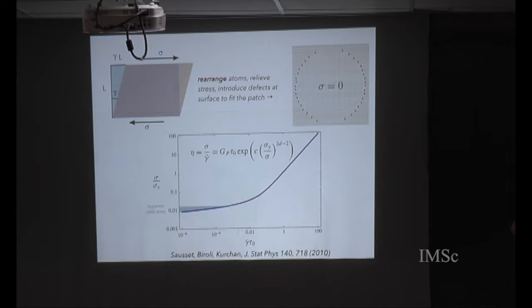But once you shift them back, you will have a boundary. This is a single crystal, but once you shift them back, you will have a boundary, and the energy will be completely localized at this boundary, where you have to put in dislocations. So now you can make a typical first passage time like calculation, and from the time and from the stress which you have relaxed, you can calculate a viscosity, and you can plot this viscosity. This viscosity turns out to have an essential singularity at stress equal to 0.